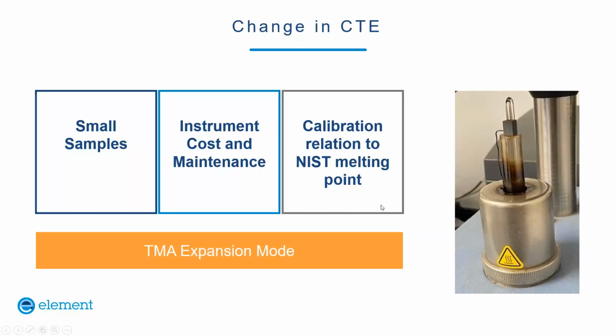And then the movement of the rod is measured with an LVDT, or linear variable differential transformer. Usually we heat up at 5 degrees C per minute, and the data is reported as a curve where the change of length is plotted versus temperature. And the slope of the resulting curve is the coefficient of thermal expansion, or CTE. It's actually coefficient of linear thermal expansion because we're just measuring in one direction. Because standards like indium have sharp melting points, calibration is easier to standardize, and there's less lab-to-lab variation.